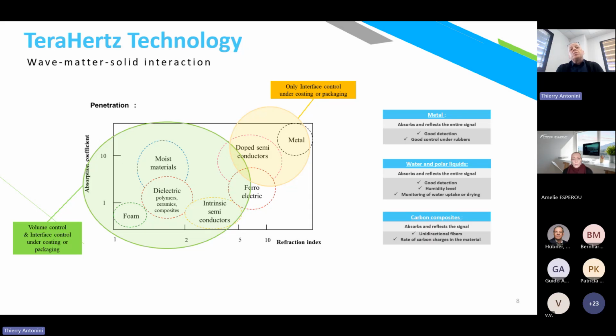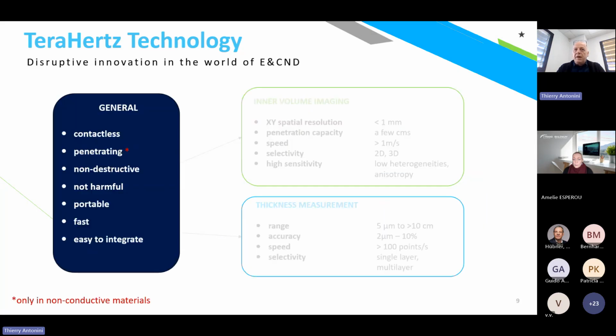Carbon composites also, you can imagine, are quite conductive. So the only application we can address for such a material is when the carbon composite is a unidirectional tape, we can penetrate, but as soon as the directions of the carbon are mixed, it's not possible for our wave to penetrate. It's not the case, obviously, for glass fiber, which is a non-conductive material. So glass fiber, aramid fiber could be easily penetrated by our waves.